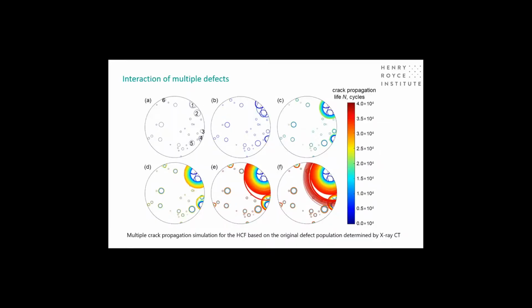And the other point to note is that, of course, in cases where you have lots of defects, you can get multiple effects. So here we can see how defects that are presented nearer to the surface tend to be the critical defects. But this modelling work just shows how defects can grow from individual defects and then join up to form larger cracks, and those multiple effects can lead to shorter lives in the final component.